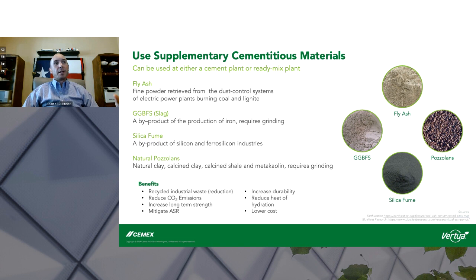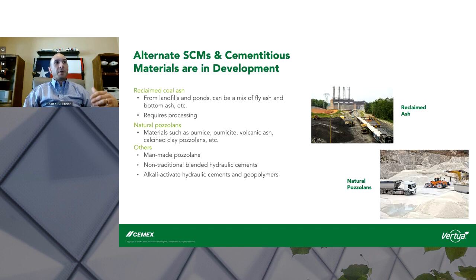around the U.S. What's really important here to understand is SCMs do two key things for us. Number one, they increase the durability of our concrete to fight against things like alkali silica reactivity, freeze-thaw durability, things of that nature. But it also reduces the carbon footprint of our concrete by a significant manner. So every percent or so that you put into your concrete mix, typically it lowers your carbon footprint by about 1%. Very impactful.